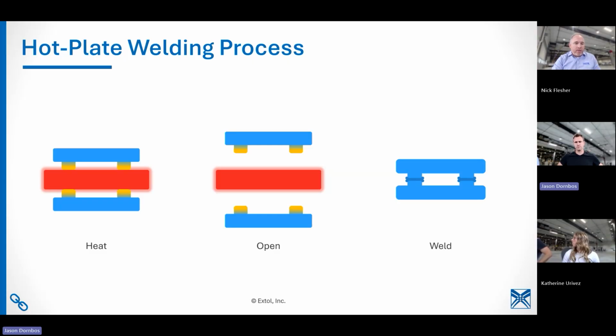So Jason's pulled up the hot plate welding process. If you're new to hot plate welding, it's a very simple, straightforward process where there is a central heat plate. The two plastic parts are on both sides of the heat plate. You make contact with the heat plate. Then you have an open time where the heat plate has to get out of the way. And then our weld process is a very precisely controlled position or force. You just need, for really all plastic welding, heat and pressure. And the hot plate welding process is that.